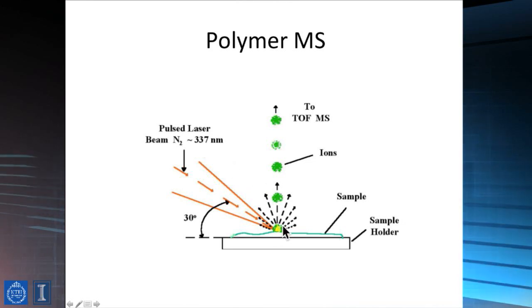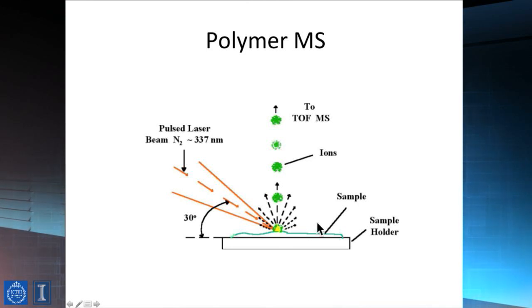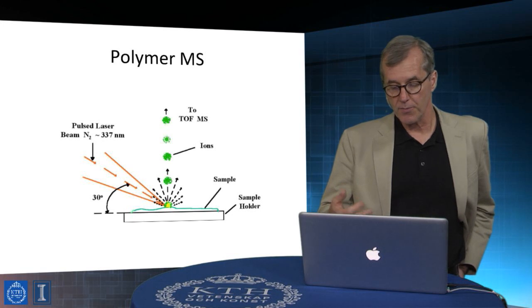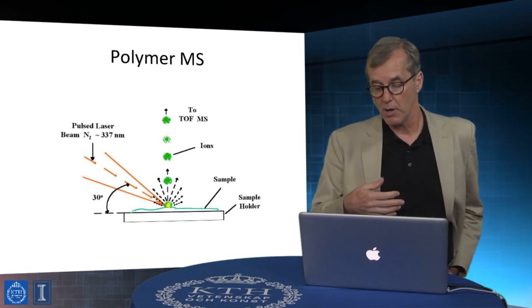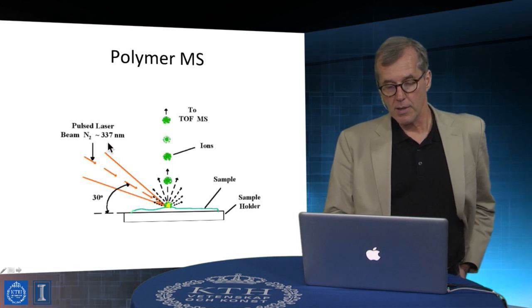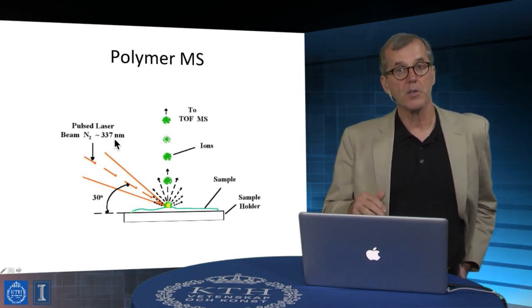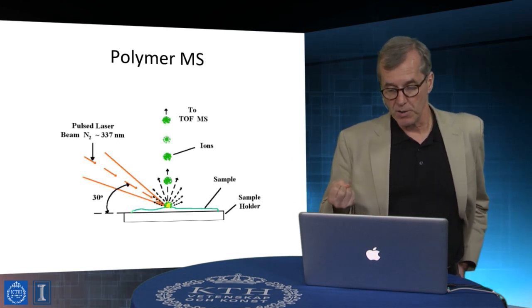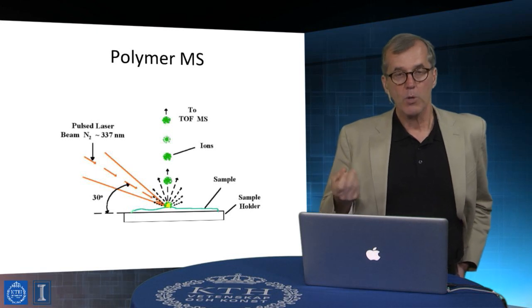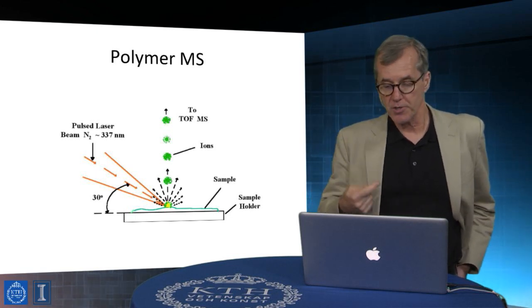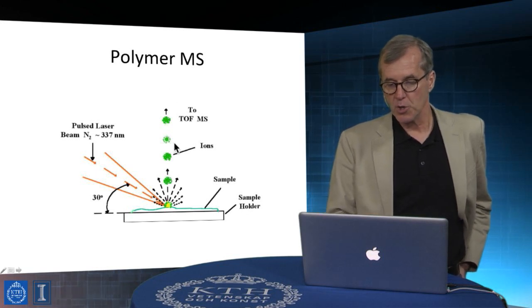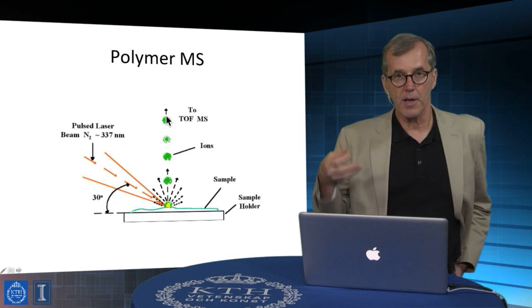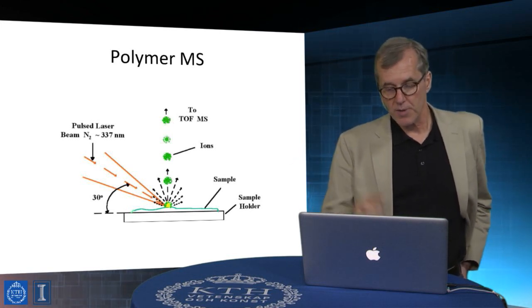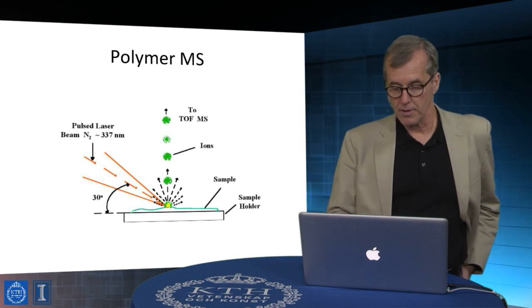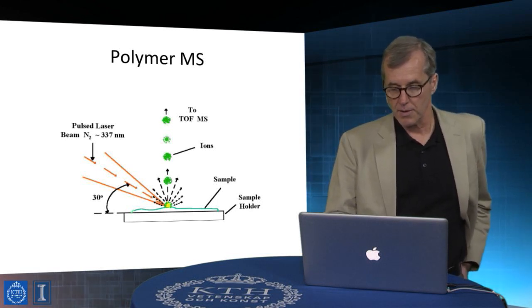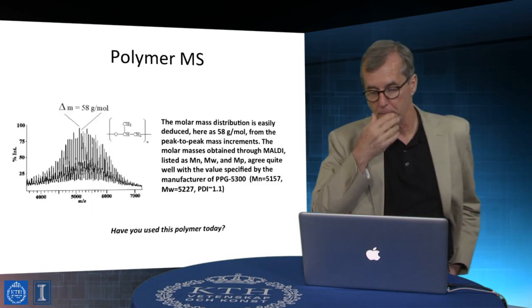The matrix material is sensitive at that wavelength, whereas most of the materials of interest, for the kinds of analyses that we care about, would not be. And the excitation event with that laser leads to the decomposition of the matrix, a little puff of explosion, which also attaches a charge to the molecule. Once it's charged, it can then be pulled into the mass analyzer via the electrodynamical fields that are used in this instrument and mass analyzed by time of flight.